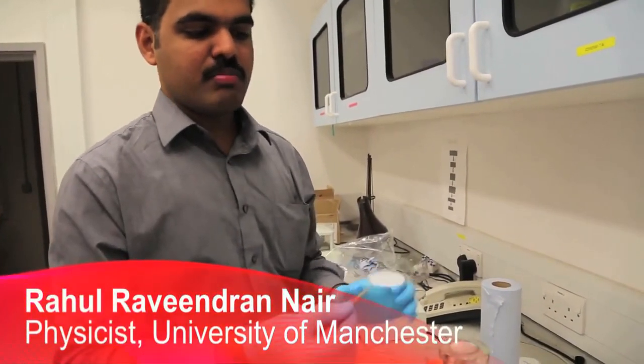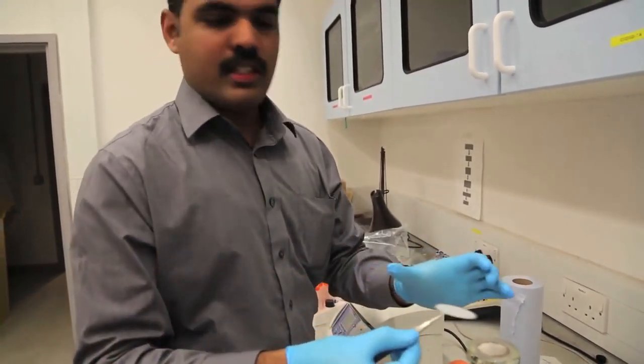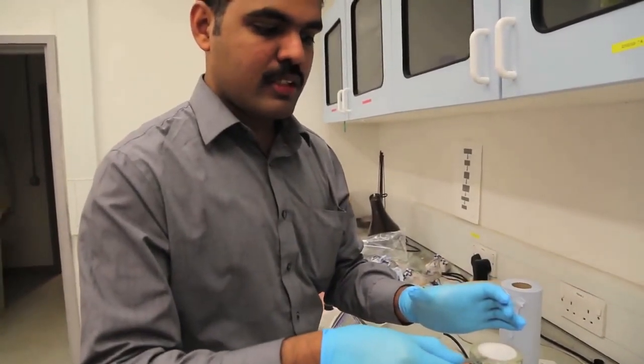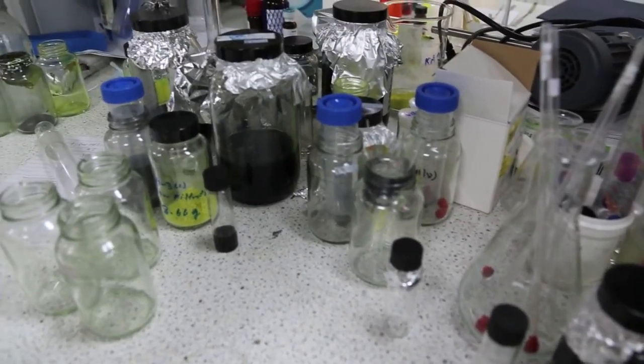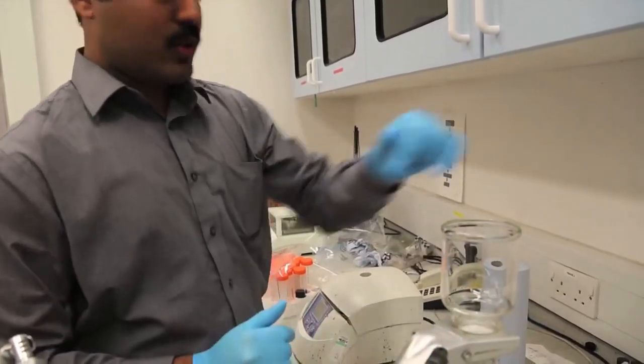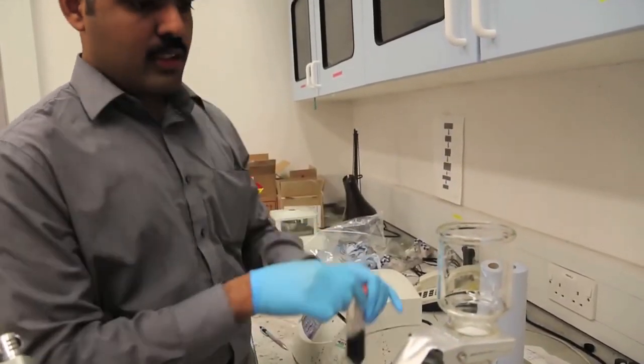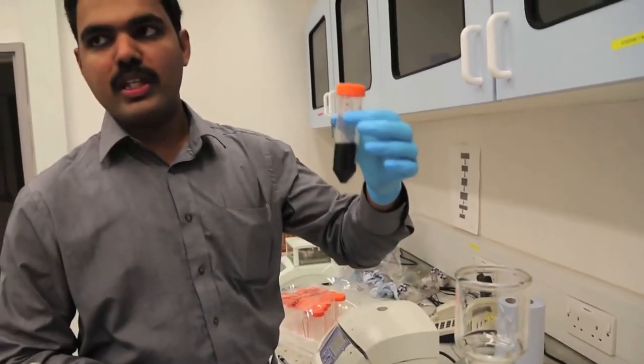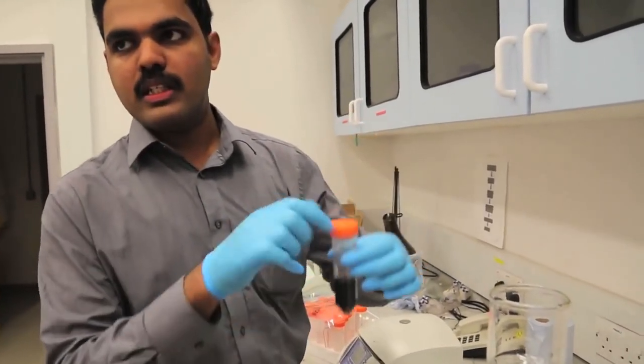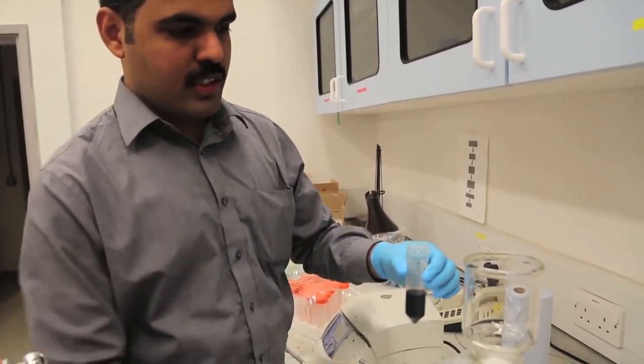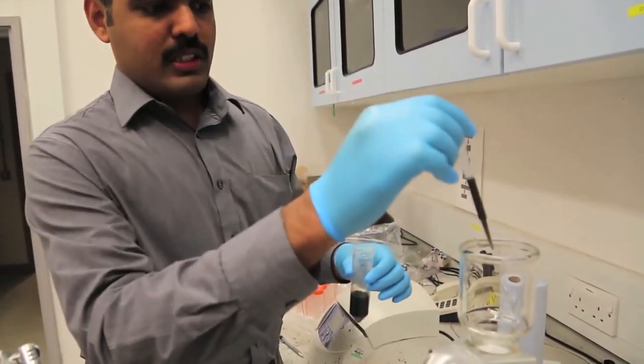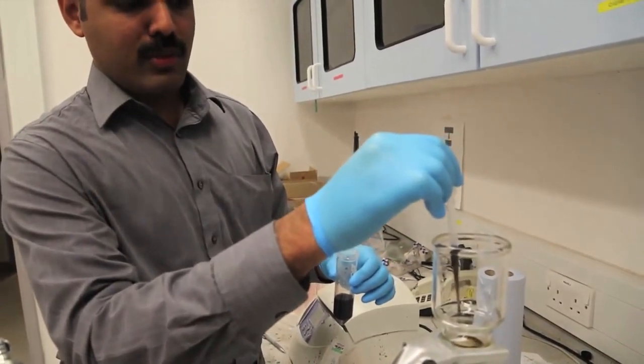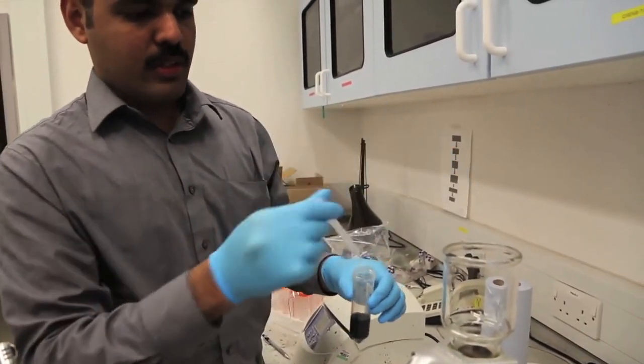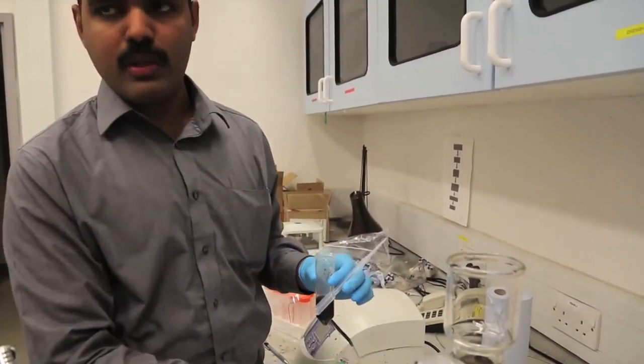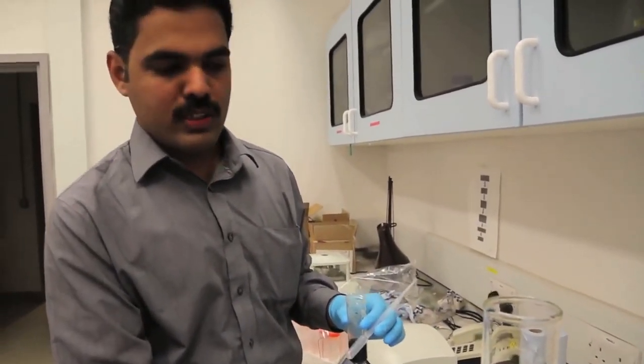So we use this kind of porous support material to deposit graphene oxide sheets to make a freestanding membrane. So you use a porous support, then you pour graphene oxide solution over here. So this is a graphene oxide solution in water. It has single layer graphene oxide dispersed in pure water. Then you use this water on top of this porous alumina membrane. Then you start pumping using a vacuum pump.